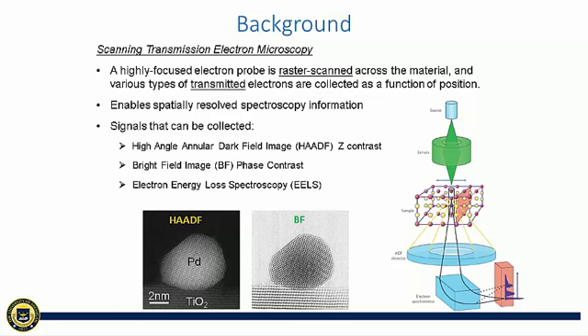If we collect electrons that are scattered at relatively low angle with respect to the optical axis, then we'll have a bright-field image. It's a phase contrast image, similar to HRTEM. And those images are formed by elastic scattered electrons. If we collect electrons that have transferred a sufficient amount of energy to knock out core shell electrons of the material, then we'll form electron energy loss spectroscopy. Below are images showing palladium nanoparticles supported on TiO2. The left one is a HAADF image, and the right one is a bright-field image.